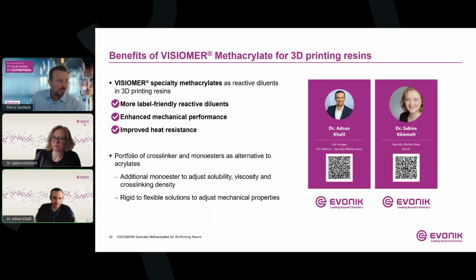So in general, maybe one can say that a too low energy input results in a not fully cured final system that leads to lower mechanical properties, and a too high energy input can lead to an overcuring of the material, which can lead to warpage, microcracks, and inaccuracies that later heavily influence the final properties.